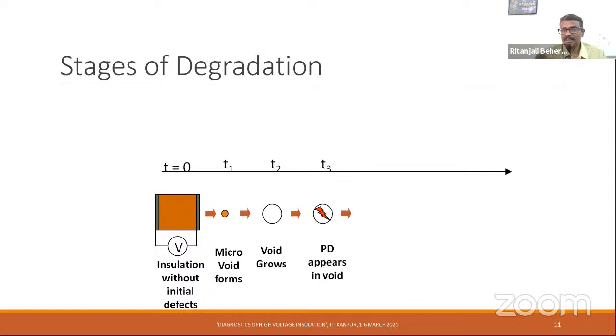And in fact, only at the last stage, I have mentioned it as a PD appears. The reason is that definitely the void cannot grow from micro void to the bigger void without the PD. Definitely, there is a PD that will be taking place. The only thing is that it might not be at the detectable level. This could be less than 2 pC or whatever, but only beyond 2 pC are we able to detect it and then measure it by using a PD detector. So it will be taking place, but however, after the bigger void forms, the PD starts.